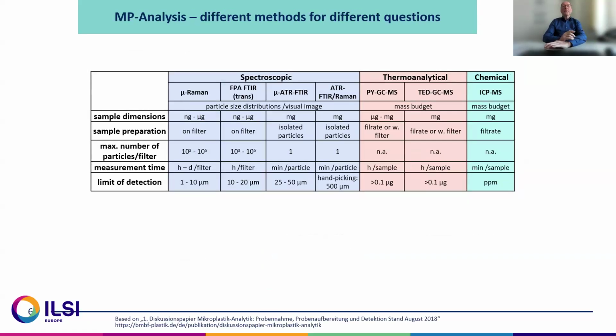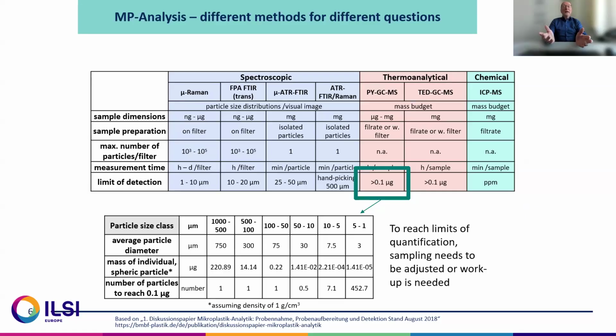If we go to the thermo-analytical methods like Pyrolysis-GC, you see the detection limit is around 100 nanograms. And if you have only small particles in a sample, then to reach the limits for quantification, sampling needs to be adjusted for a longer time or a workup is needed.